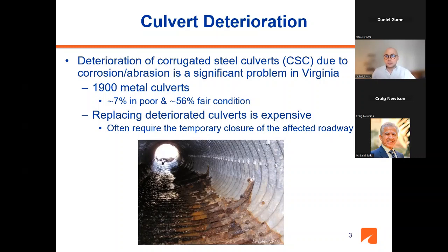This deterioration usually occurs because of corrosion of these culverts. These culverts are usually made out of galvanized steel, which gives some corrosion resistance. Nonetheless, over time, with the water, they corrode, and also because of the abrasion from not just the water, but all the particles that go in this water, gravel, etc. Now, replacing these culverts is fairly expensive and often requires temporary closure of the affected roadway. So this is a very significant problem for us here in Virginia, and very likely in many other states in the United States.